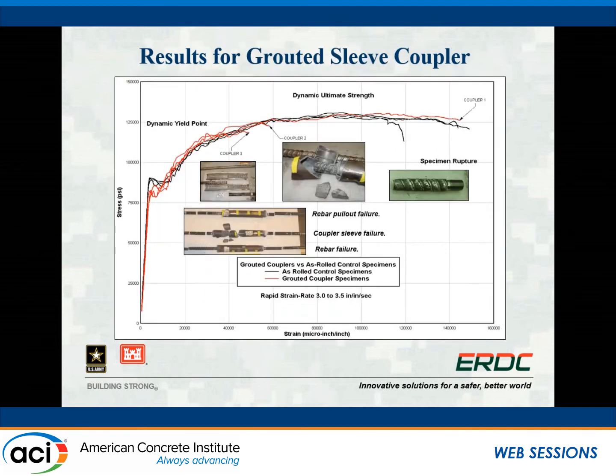The grouted sleeve couplers achieved equivalent tensile strengths, but had some significant reductions in ductility depending on the failure mode of the bar. In ideal cases where we get rebar failure outside of the coupler, we get acceptable levels of ductility and ultimate strength. But in other cases, where the coupler itself failed, the sleeve failed, or the rebar just pulled out of the grout sleeve, we get reductions in ductility.